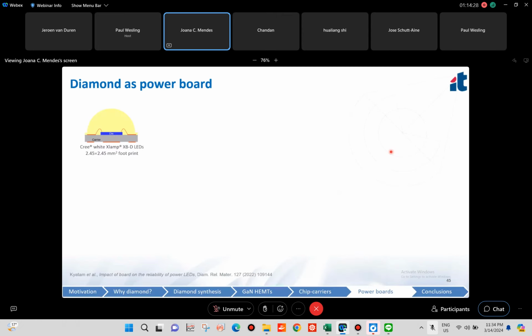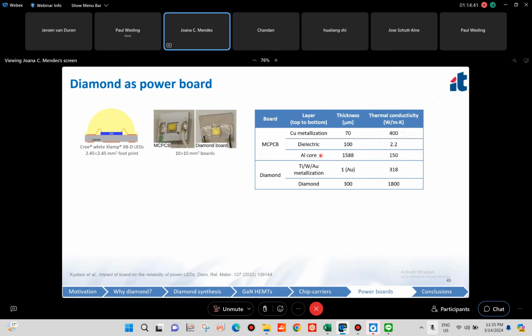So we used the same LEDs, and we simply bought a metal core printed circuit board as advised by the manufacturer, and we bought a diamond board. So here I have the characteristics of the board. This is a standard MCPCB board with copper metallization, dielectric insulator, and an aluminum core. And the diamond board that we bought had a 300 micron thick diamond plate with 1800 watt per meter Kelvin thermal conductivity, with a titanium tungsten gold metallization provided by the manufacturer.